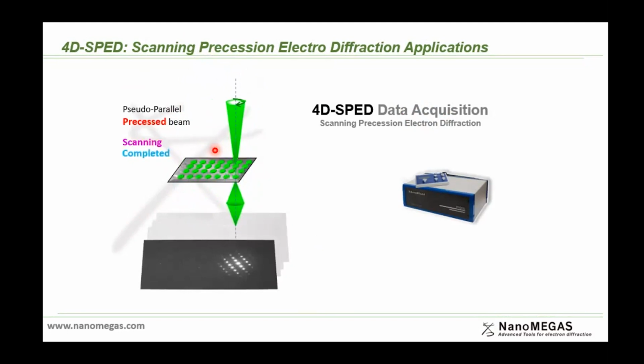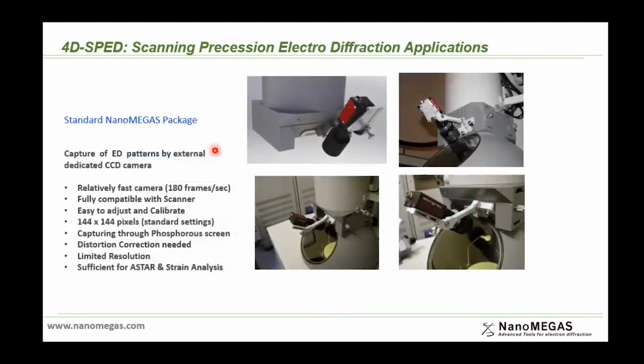So because today we'll speak about a combination of our technique with direct electron cameras and Merlin camera, I will focus a little bit on this. So the standard package is using a CCD external camera that collects data from the phosphor screen. And this is a method that has been applied for the last 12 years or more, and quite successfully. And even if the camera is not the best quality, we have sufficient data to obtain quite good quality of orientation and phase maps.